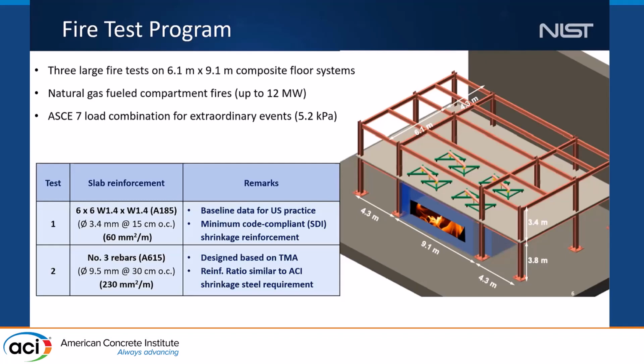The effective area is about 60 square millimeters per meter of slab width. And in test number 2, we replaced this wire mesh mat with number 3 rebars in both directions at 12-inch spacing. This particular design scheme is based on the TMA method, incorporating the tensile membrane action. The reinforcement ratio is very similar to the ACI shrinkage steel reinforcement, which is 0.2% of the concrete area.